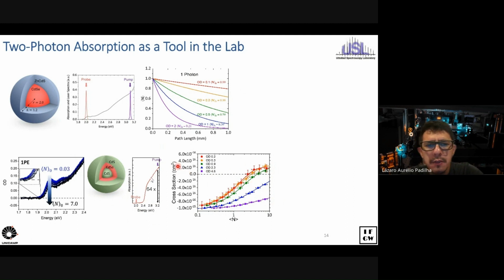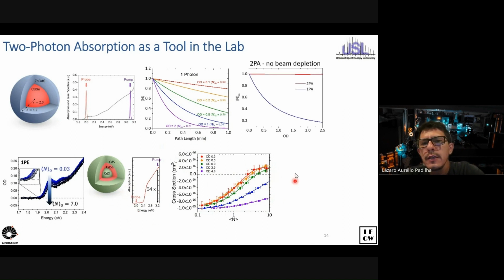So if I have an optical density here of, let's say, 0.6, which would make your data already kind of problematic. But if I make it 0.6 here, it means that the optical density at the probe would be like 0.01, which is nearly impossible for us to actually have nice signal to noise to be able to interpret the data. So one way to do this is to use two-photon absorption, where the optical density is virtually 0, and you see the beam is not depleted at all through the sample.